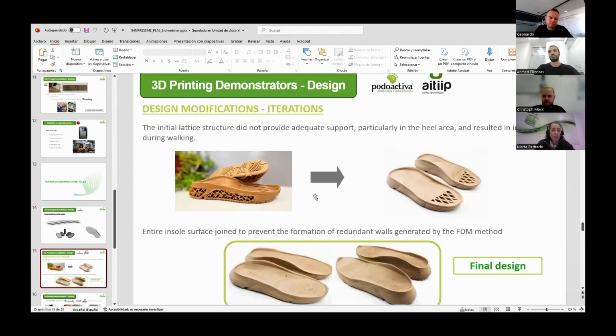The initial design, you can see there, is very nice. You can see the inside of the structure of the inner shoe sole, but this initial lattice structure didn't provide adequate support, particularly on the heel area. So it resulted in instability walking. So what we did, together with Podoactiva, was decide that the entire shoe sole was joined together to prevent the formation of redundant walls generated by the fused 3D printing method.